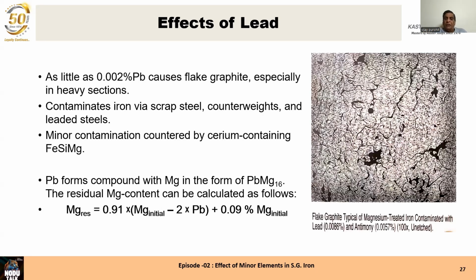Effect of lead. Lead is a very dangerous element to be present in any raw material. Lead causes flake graphite. Look at the microstructure. The full structure is full of flake graphite. You hardly see any nodules over there. As little as 0.002% lead causes flake graphite, especially in heavy section castings. It contaminates iron via scrap steel, counterweights, and leaded steel. There are some steels with lead content deliberately added as alloying elements, but if that steel comes into your raw materials, you will have havoc with your SG iron casting.